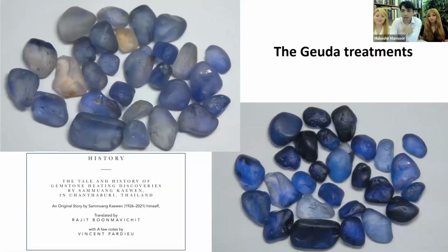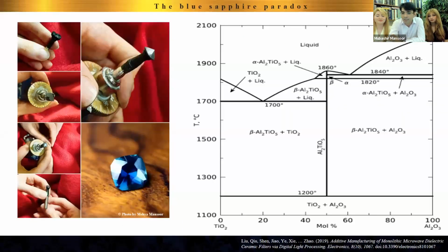Now, coming back to these sapphires here, we are mentioning that we are dissolving rutile, the titanium dioxide, into the alumina structure, into the sapphire. How can we describe that in a phase diagram? Well, the problem is that there is no solubility in this phase diagram for rutile. Actually, this is very interesting, because what is this diagram showing me? Look at this particular side. It's 100% alumina. This means on this side we have 100% sapphire. And as I move to the left, I increase the concentration of rutile.